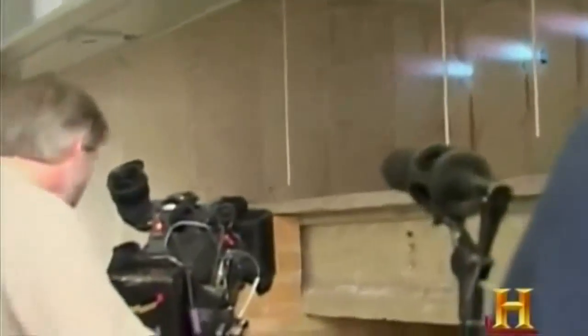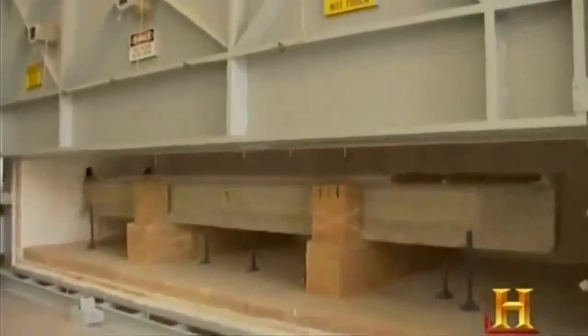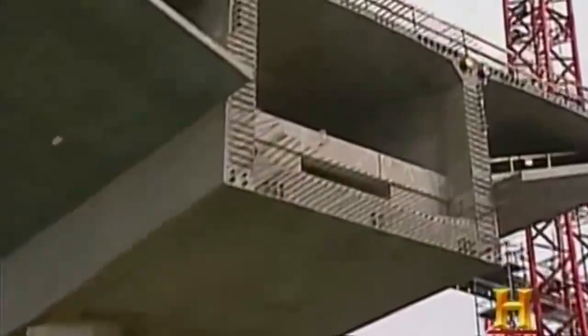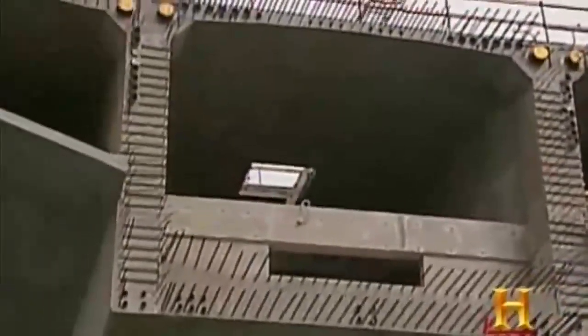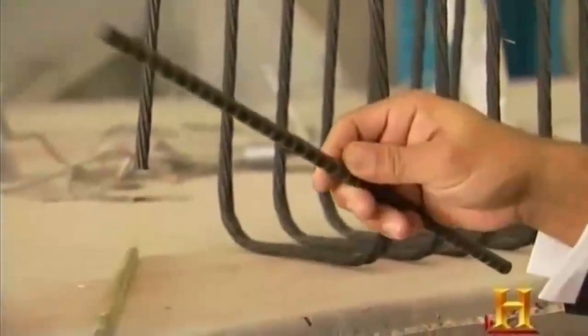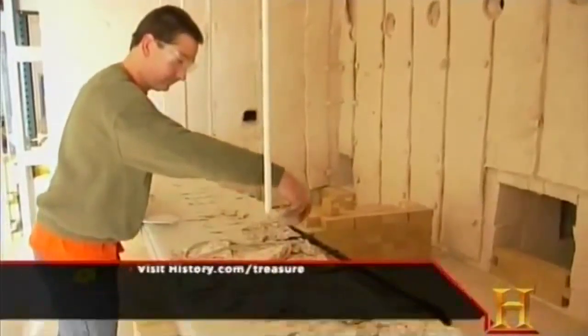We intentionally have the furnace on very negative pressure right now, so it's drawing a lot of room air in to keep the area around here cooler. Otherwise, we might burn up some of the cameramen and myself in particular. The door closes again, putting the pressure and the heat back on the concrete beam. While conventional concrete beams have steel rebar inside, this beam has been reinforced with carbon fibers instead. These fibers, developed at the center, are stronger and less corrosive than steel, but are also more flammable. After about 20 minutes of full heating, the concrete has crumbled and the fibers are singed.